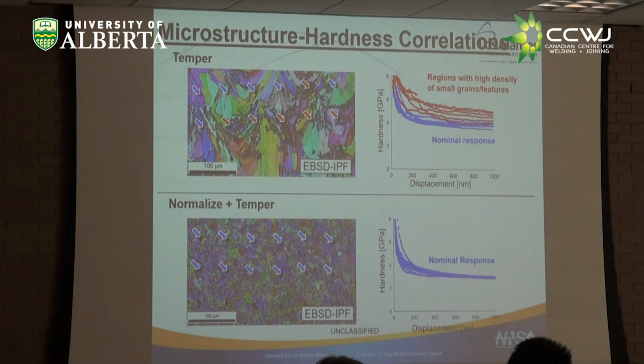I guess the thing I really want to show you is this here. So we looked at the sample as the as-welded or the tempered, and this is basically the microstructure hardness correlation. So the little speckled region, if you put the nanoindenter into the speckled region, which has a lot of carbides and martensite, it would show higher hardness, and that is the red arrows there. So whenever they pushed down into the martensite regions, they had higher hardness, whereas the regions that were not the speckled regions had the blue, lower hardness typically. Again, that was a clue to us that that was martensitic. But the normalized and tempered had a much more uniform response here, basically.